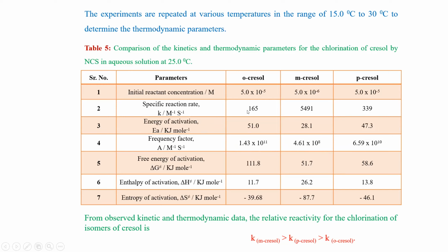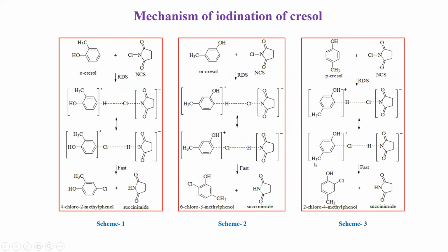So the entropy of activation is in the seventh row below. The M-cresol has minus 87.7, the P-cresol has minus 46.1, and then O-cresol is minus 39.68. So the entropy of activation is much more negative for M-cresol. That is, the reactivity of the M-cresol is much higher than that of the P-cresol. We have seen here this study of the relative reactivity of the isomers of cresol.